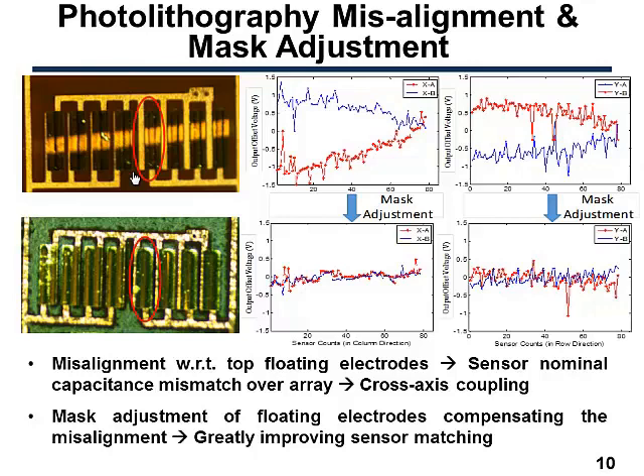So in order to solve this problem, before we deposit the floating electrodes, we adjust the mask, and you can see here the alignment has been much improved, and the sensor nominal capacitances are quite consistent. This can reduce the cross-axis coupling significantly, which means there will be minimal cross-coupling from vertical pressure to y-axis shear outputs and vice versa.